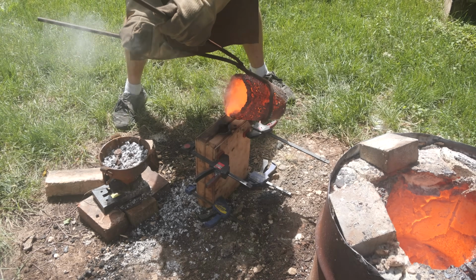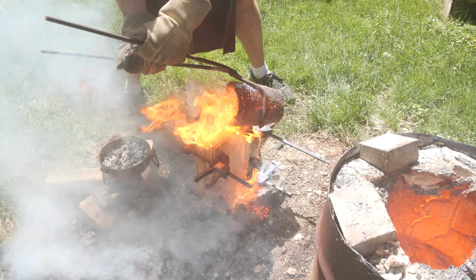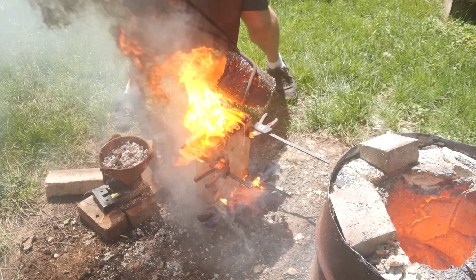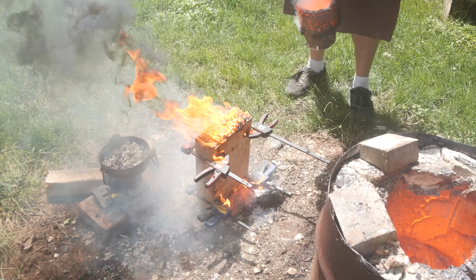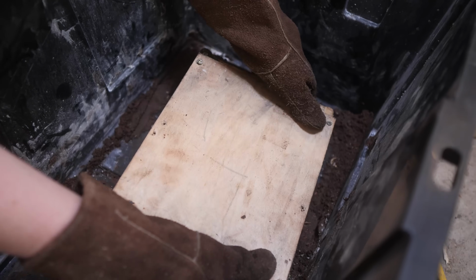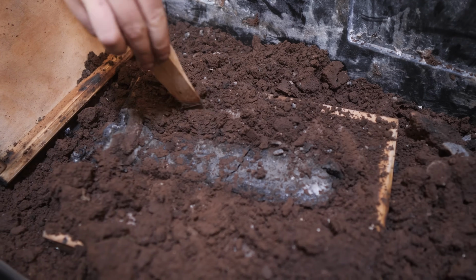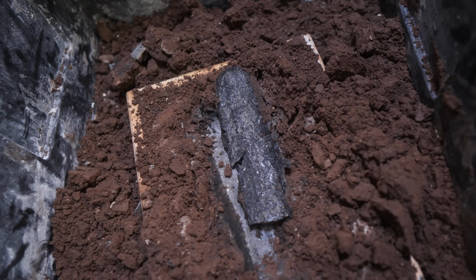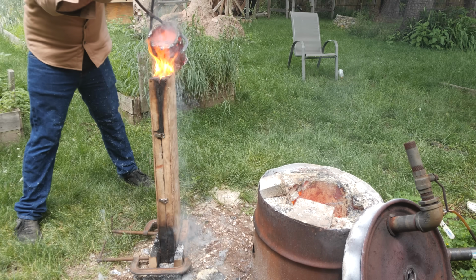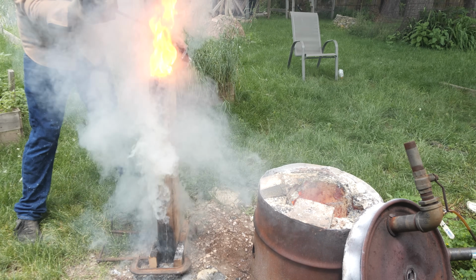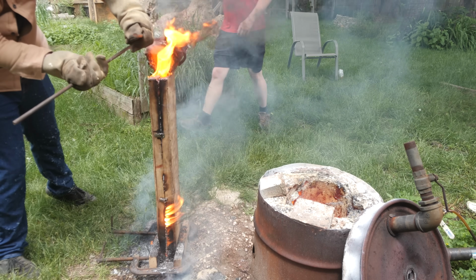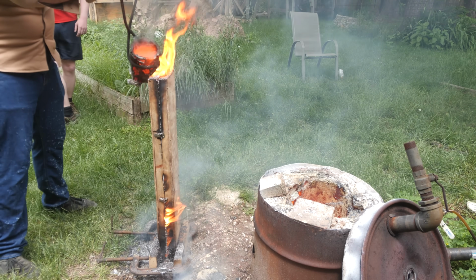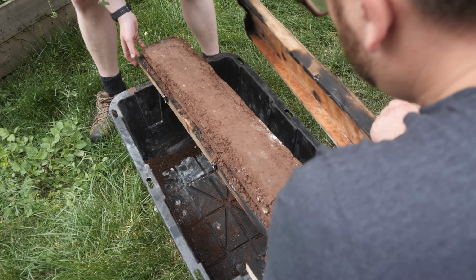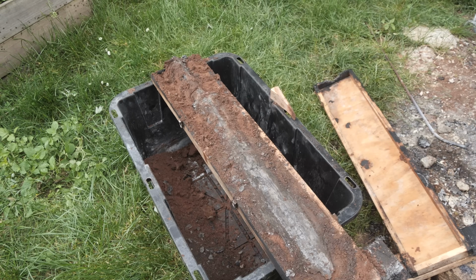Meanwhile, I still wanted to attempt a full-size sword cast, so was curious to try a 50-50 mix of salt and borax. This wound up being thicker, more like the borax, but was still a pain to pour accurately. The result was surprisingly solid, but did not fill the full blade shape very well. So next attempted with the full blade cast. It's still very runny at this point, and ended up losing a lot pouring out of the edge of it. But after opening it up and carefully exhuming it, we actually managed to get a full intact sword.